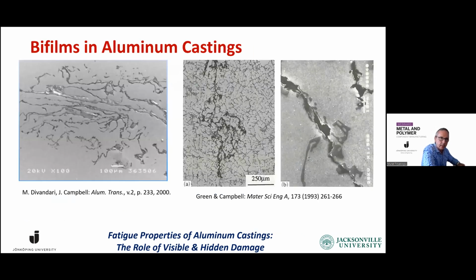So the entrainment defect is what we call the bifilm, the folding over of the liquid surface film. And in the process, we also have air bubbles, which leave behind oxide trails, and we're going to show some of them now. Here are some of the biofilms that were found in aluminum castings. On the left, you see one that is very crumbled, and just in the metallograph, it was cut through it. You can even see one half of the film over here presenting itself. There's another one that is completely folded, and most of the times these biofilms are invisible in X-rays. They become visible only when you look at the fracture surface. And when you zoom in into this area, you see that there is no bonding between the two sides of the bifilm. So it is definitely a crack.